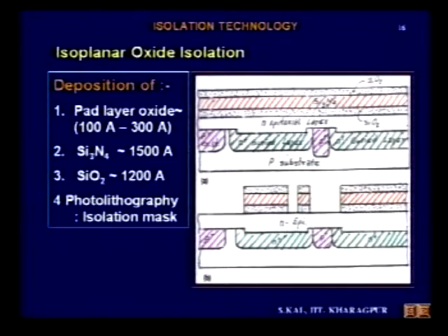And the top layer is required for lithography compatibility, because you have to pattern the nitride. To do that, you have to go for lithography, and there you need a solution which will etch silicon nitride but not etch photoresist. That is very difficult, because the silicon nitride etchant is normally boiling phosphoric acid. In that case, photoresist sometimes will also wash away. It is used at high temperature, so that is the problem.